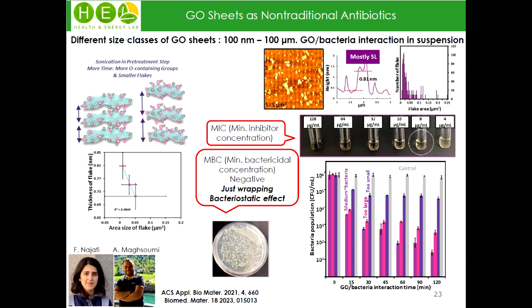In another research with my postdoc and master students, we prepared 7 classes of graphene oxide sheets in terms of size, from 100 nanometers to hundreds of micrometers, and we found that the interaction of bacteria with the graphene oxide is strongly dependent on the size of the bacteria and the size of the graphene oxide sheet.